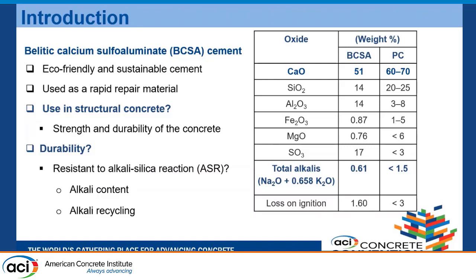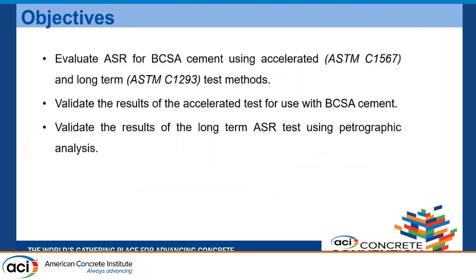But the other thing that we need to look at is, do we have alkali recycling? For that, what needs to be checked is that calcium hydroxide can still make the reaction continue even if you have less alkali content. So since BCSA has belite in it, it's important that the performance for ASR is checked. So that's the objective of the research.